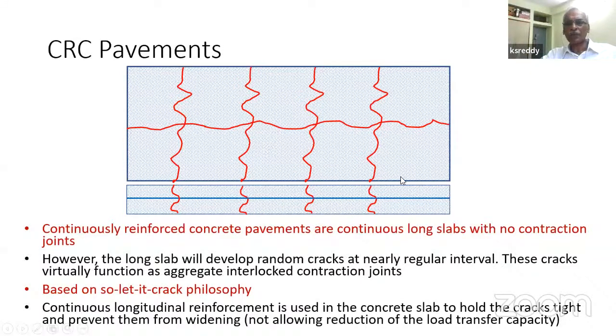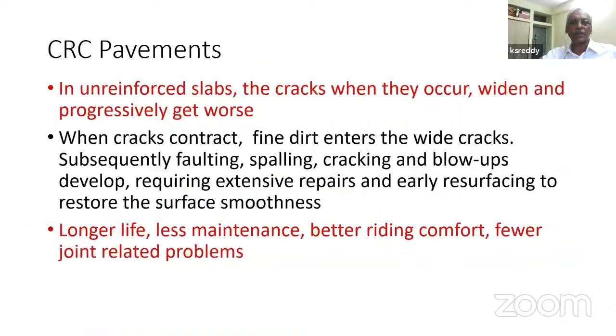So the principle of this continuously reinforced concrete is, we know that there is going to be cracking. So it is based on "let it crack," right? People should accept that this is a pavement which is going to have cracks. When you cut grooves, they're in a regular fashion, so people will accept that. But this surface will have irregular cracks, so one has to accept that. Right? And we provide continuous reinforcement, as I already mentioned, to ensure that adequate load transfer is continuously maintained. The cracks do not open.